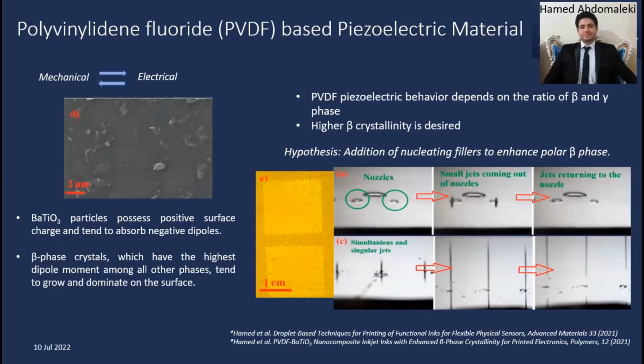So when you infuse barium titanate particles into them, you basically alter their crystal structure, and then you increase the crystallinity by a few percentage. And then what we did was basically convert it into a very successful dispersion, and then used inkjet printing to print this material into making a pressure sensor. But what we found was that yes, adding barium titanate does increase the crystallinity of the material, but not so much. It still didn't stand a chance to make a very sensitive pressure sensor for a biomedical device.